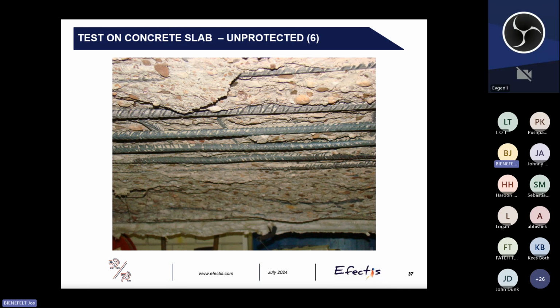And this picture gives a more detailed view of the surface. You can actually see here that spalling was so severe that it's actually behind the first reinforcement layer. This particular sample had a concrete cover of 70 millimeters. So with this test, we've lost in 25 minutes at least 70 millimeters, and at some locations even more.